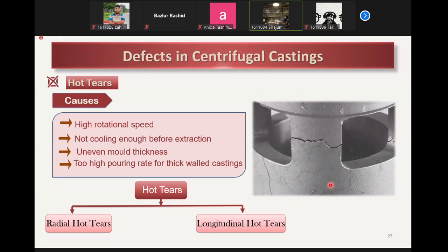A number of defects occur in centrifugal castings, which can be related to pouring, spinning, temperature, material, or coating. Hot tears are developed in centrifugal casting, especially for high rotational speed. Hot tears can occur across the circumference of the casting or transversely across the casting. They can be caused by several different reasons, like not cooling enough before extraction, uneven mold thickness, too high pouring rates, especially for thick-walled castings, etc.